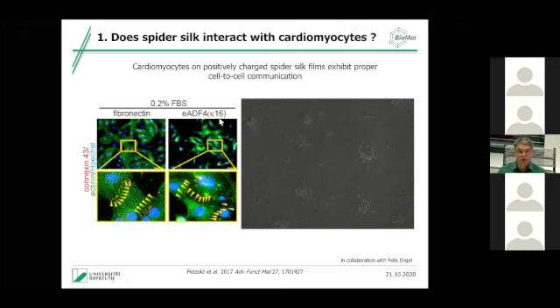And all of a sudden, so we call this protein eADF4(κ16), for engineered Araneus diadematus, so that's the spider, fibroin 4, so this is the natural counterpart, kappa 16. Kappa stands for K for lysine, and we have 16 lysines in there. And if we make this engineered spider silk protein, you see that the cardiomyocytes now all of a sudden attach to the surface, they spread, they proliferate, they connect, and in the movie you see they even start to contract after 2 or 3 days. And we even could keep beating cardiomyocyte cultures for more than 60 days in culture.